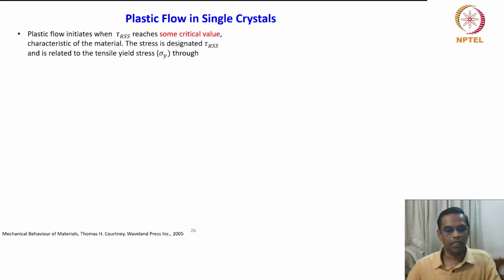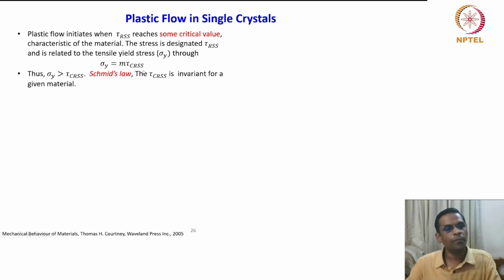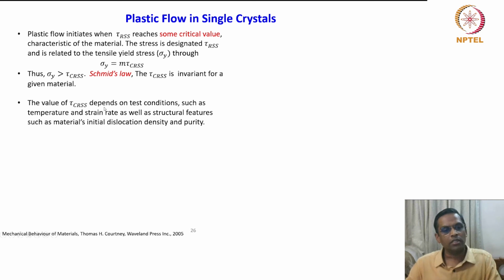So if you look in a little more detail at plastic flow in single crystals, we have seen that plastic flow initiates when tau RSS reaches some critical value characteristic of the material. The stress is designated tau CRSS and is related to the tensile yield stress sigma through this relation: sigma y is equal to m times tau CRSS. This is also known as Schmid's law. The tau CRSS is invariant for a given material. The value of tau CRSS depends on test conditions such as temperature and strain rate, as well as structural features such as the material's initial dislocation density and purity.